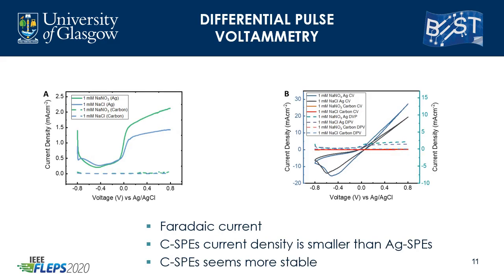To better analyze faradaic currents, differential pulse voltammetry was employed. DPV is a highly sensitive technique that improves the signal-to-noise ratio of the voltammogram. The capacitive or background current is nearly eliminated by allowing sufficient decay of the non-faradaic current. By analyzing the left figure, we can see most of the cathodic peak seems to come from non-faradaic reactions, as the DPV shows almost no redox peak from minus 0.8 to 0 volts for silver. A possible explanation is the occurrence of an enhanced pseudocapacitance on the surface of the silver electrode in the presence of salts, which can be better understood by the electrochemical impedance spectroscopy studies.